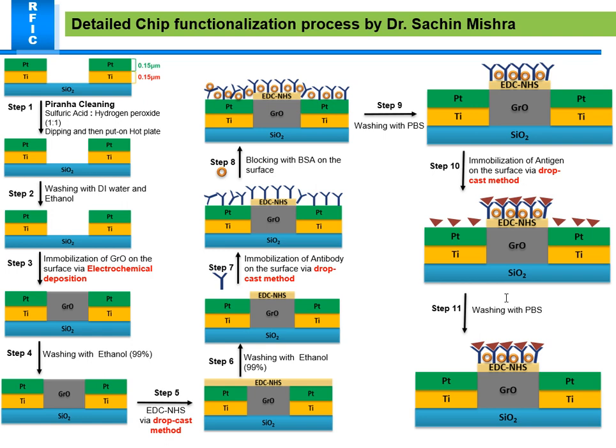So as per your comment this morning and in today's meeting, I have to reduce the thickness of the graphene oxide. As per your comment I just made a thin layer of graphene oxide in between the electrodes, and all the things will be reduced because of the graphene oxide thickness. And this is the whole process that I have followed until the washing with the PBS.